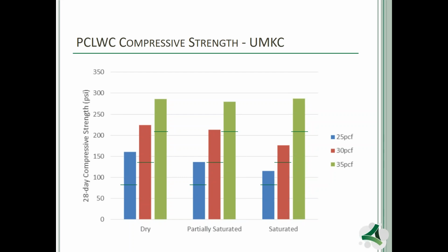Some questions have come up in reference to compressive strength with saturation of the pervious cellular concrete. Again, at the University of Missouri at Kansas City, some studies were done on both dry pervious cellular concrete, partially saturated and fully saturated. I'm going to ask you to ignore the fully saturated material because that is truly under laboratory conditions and will never affect true field conditions, because you're not going to be able to infiltrate 100% of those voids. The black lines on the graph demonstrate your minimum requirements as per the ASTM standards of compressive strength requirements, and in all cases, they exceed the minimum requirements.